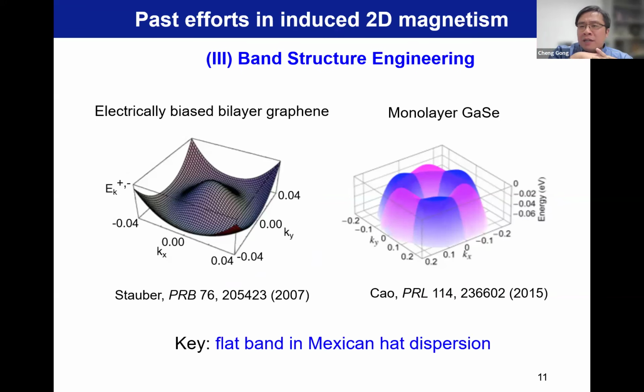So the one is band structure engineering. I think this is a very exquisite way. As long as in a material you can find a flat band, and then there will be a large density of states within a very narrow energy window, then likely you can satisfy the Stoner instability and cause the ferromagnetic phase change. So in some materials, especially based on theoretical calculation, people begin to find, for example, in bilayer graphene, when you apply electric field, you can create a small gap, and then you have a flat band on the band edge, or highly p-type doped gallium selenide.